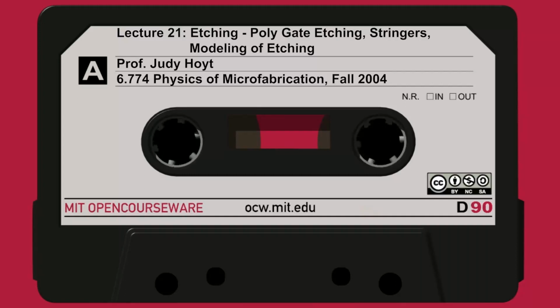Selectivity we care about. As we're etching this polysilicon, we don't want to etch away the resist that would be masking it on top, or whatever mask material we're using if we're using a hard mask of SiO2. So selectivity of the etched material to the masking material is very important. That's one type of selectivity.